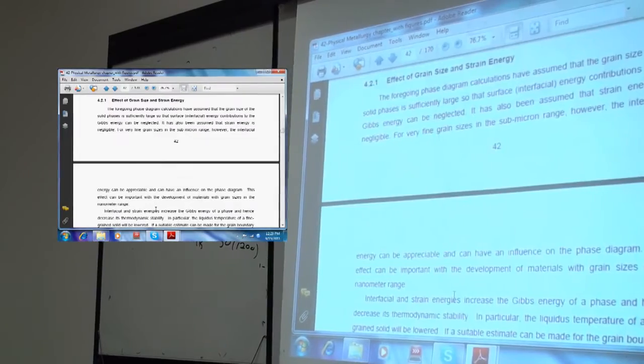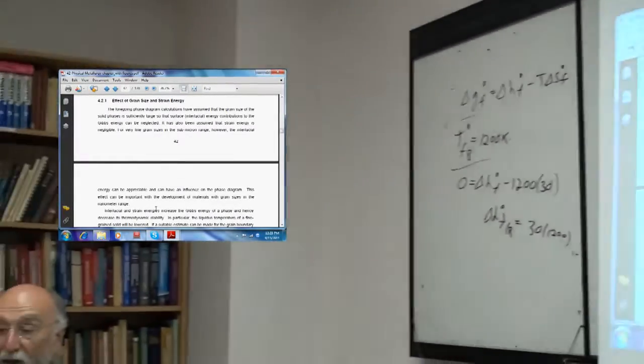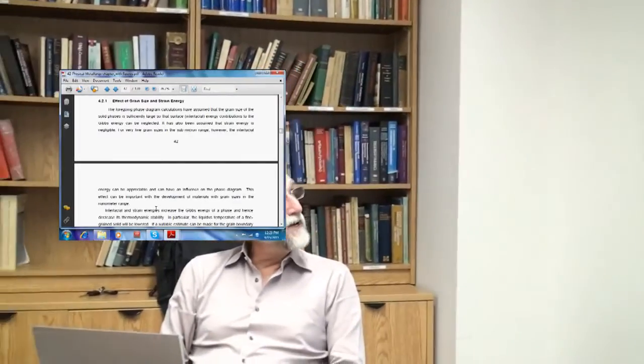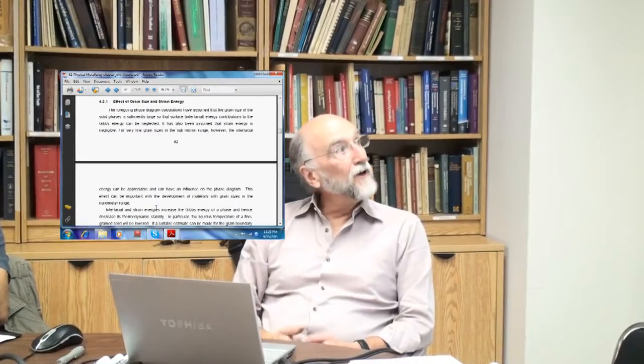Something else I'm not going to talk about is the effect of grain size. The foregoing phase diagram calculations assume the grain size of the solid phases is sufficiently large so that the interfacial energy between the solid and the liquid is a negligible effect. You're assuming this is a big chunk of solid, small liquid. It's also been assumed that strain energy is negligible. For very fine grain sizes in the submicron range, the interfacial energy can be appreciable and will have an influence on the phase diagram. So when you have a solid and liquid phase in equilibrium, you have to take into account the interfacial energy as well, if you have very small grain sizes. And this can actually affect the liquidus temperature.